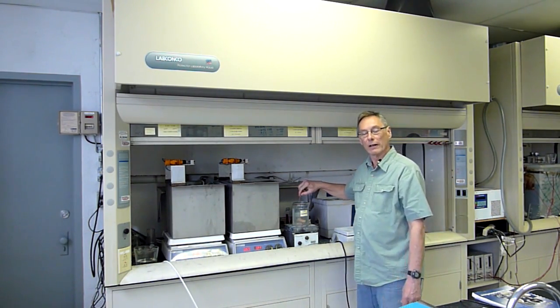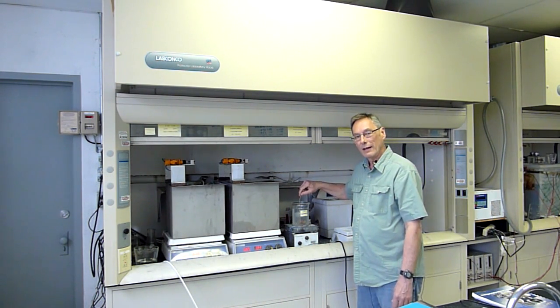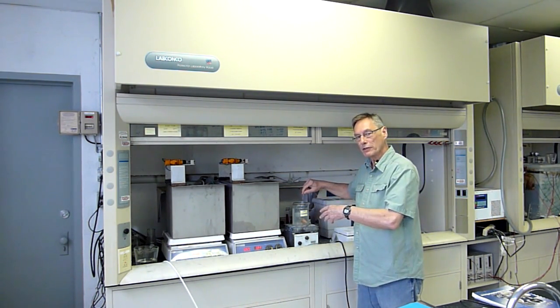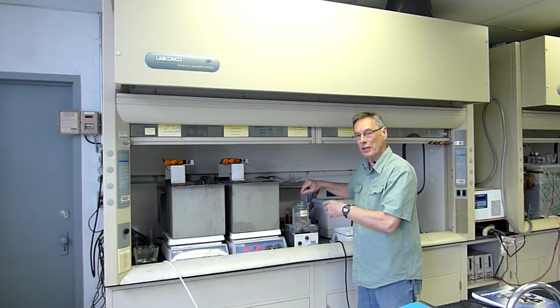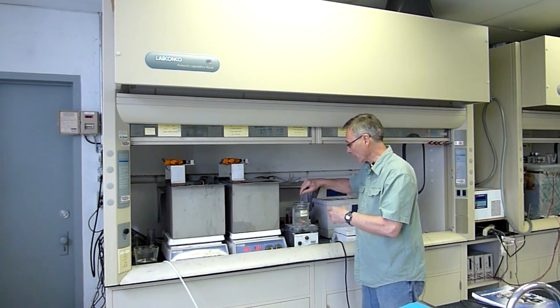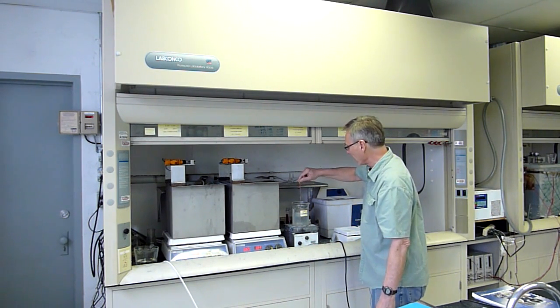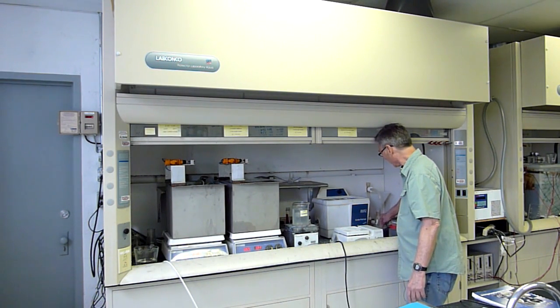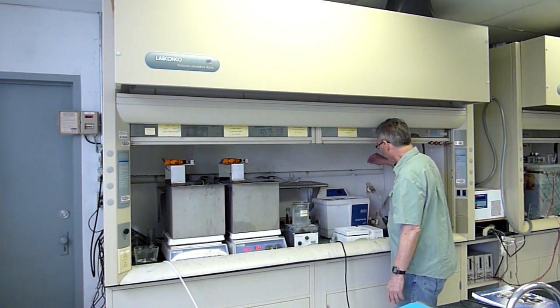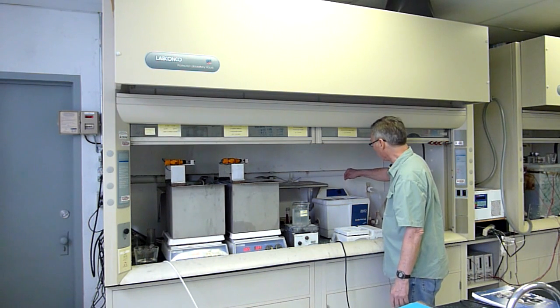Now this is an alkali cleaner right here. When we come out of any alkali chemistry, we want to do a water rinse if we're going to be into an acidic chemistry of any sort. We're coming out of an alkali cleaner. We're doing a quick water rinse.